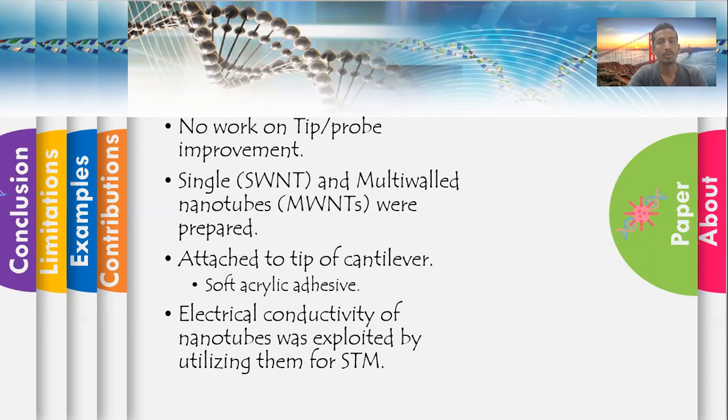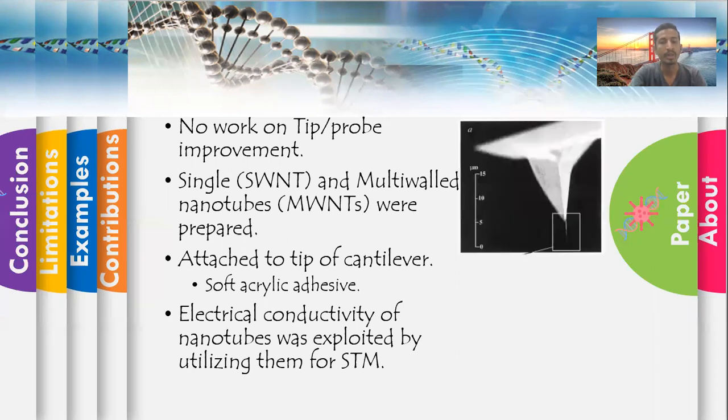So what happened in that paper is that at that time there was no or very little work actually done on tip or probe improvement. So they developed single walled and multi-walled nanotubes and then attached them to the tip of the cantilever by using a soft acrylic adhesive with the thickness of 1 to 10 nanometer. The electrical conductivity of nanotubes was exploited by utilizing them for scanning tunneling microscopy.